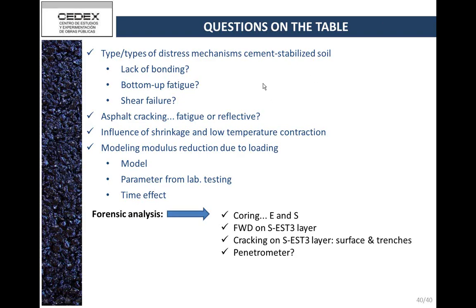Would you be expecting here to see a bottom-up cracking in the cement-treated layer? The layer is too thin to have that, but what we saw is shear. We saw debonding. We could actually determine slippage between the asphalt and the cement-treated material, and we could see the fracturing of fatigue in the asphalt, in the cement-treated materials.